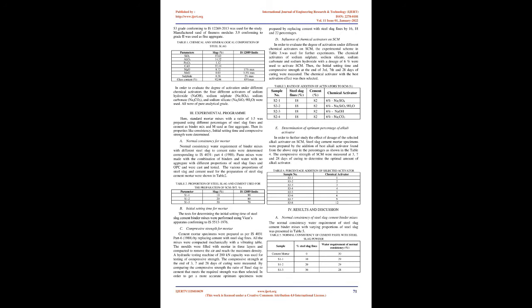3. Experimental program. Here, standard mortar mixes with a ratio of 1:3 were prepared using different percentages of steel slag fines and cement as binder mix and sand as fine aggregate. Then its properties like consistency, initial setting time and compressive strength were determined. A. Normal consistency for mortar. Normal consistency water requirement of binder mixes with different steel slag to cement ratios was determined corresponding to IS 4031, Part 4, 1988. Paste mixes were made with the combination of binders and water with no aggregate, with different proportions of steel slag fines and OPC, and were cast and tested.